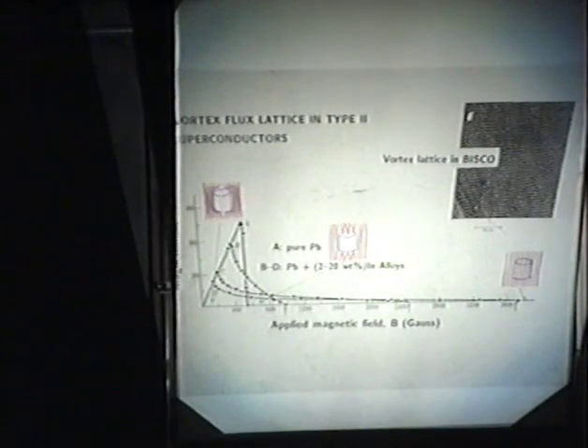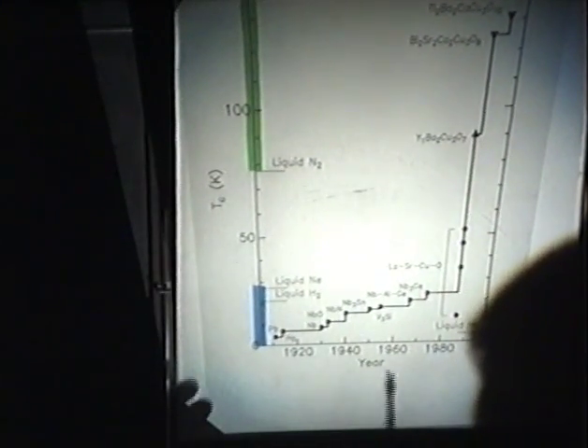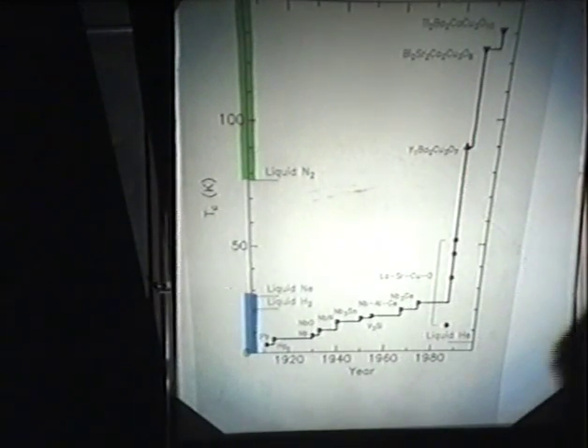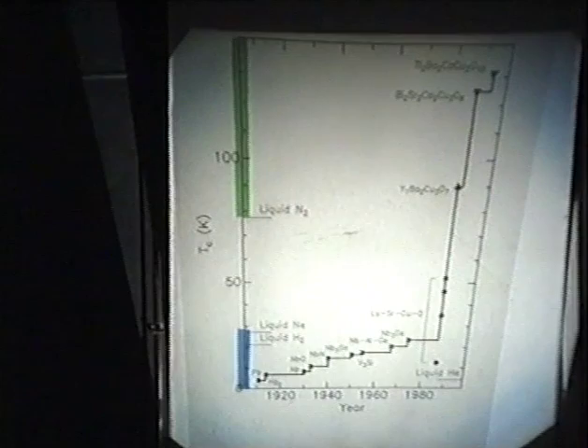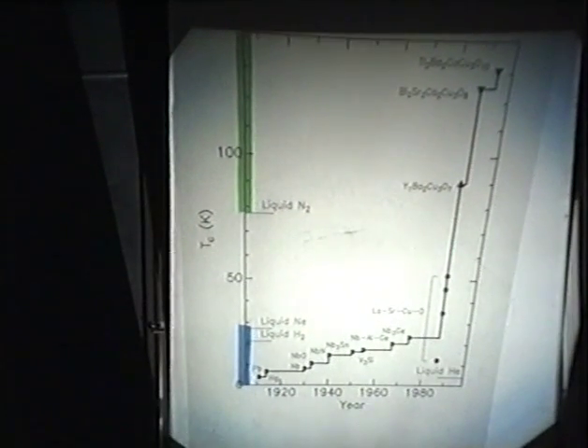And here's a picture of a vortex lattice in one of the new superconductors, which we now need to talk about. Because despite the best efforts of several decades of intensive research, still by 1970 or so, optimizing the vortex state in the superconductors has only given us niobium-3 germanium, a compound of niobium and germanium metal, which went superconducting just above the boiling point of liquid hydrogen at around 20 Kelvin above absolute zero, which is not terribly spectacular, but nevertheless, if you cool this stuff down to liquid helium, it was capable of generating